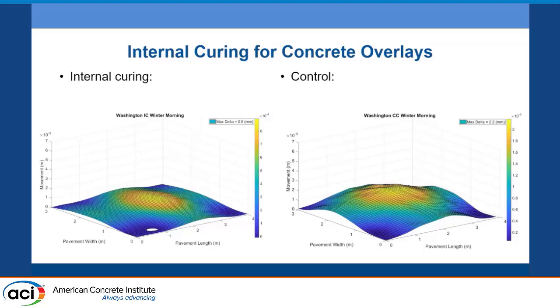This is interesting to look at because most pavements, their kind of built-in gradient is a curled up shape. And on these projects, I was reviewing the report and looking at the measurements they took at different times of year. It appears the control section here actually did have a built-in curled down shape, and it was mostly curled down, which is interesting. We've seen projects like this before. It's just not the typical behavior for concrete pavement slabs. But again, the internal curing did not have as much of a gradient as the control section, and so it generally had a flatter profile. And you would expect in the future that it would also then be a smoother pavement.